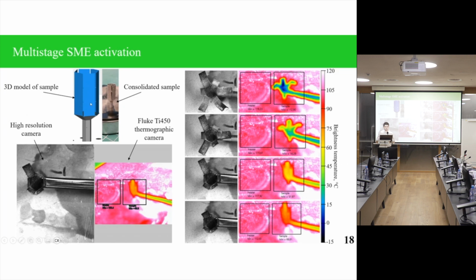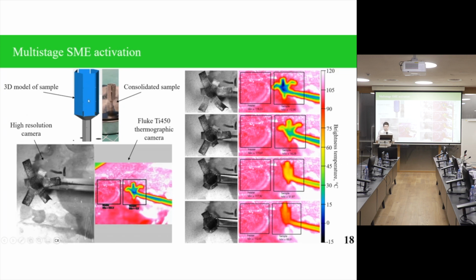Each thin-walled part was manufactured with one regime, and this sample was deformed in liquid nitrogen. Then it was placed on top of a heater and observed by a thermographic camera and a high resolution camera, and we can see that multi-stage shape memory effect activation appears. So each thin-wall part recovered its macro shape at its own temperature.